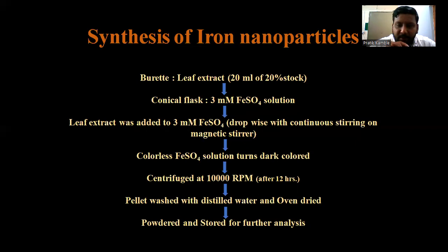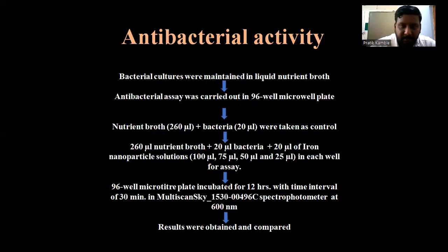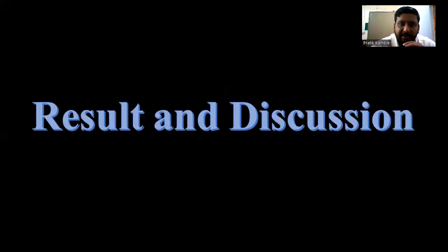The solution was centrifuged at 10000 rpm after 12 hours. The pellet was washed with distilled water and oven dried. That pellet was powdered and stored for further analysis. Then antibacterial activity. Antibacterial activity was measured by the microtiter broth dilution method. We have followed this standard protocol, and we have taken 4 human pathogenic bacteria for antibacterial activity.